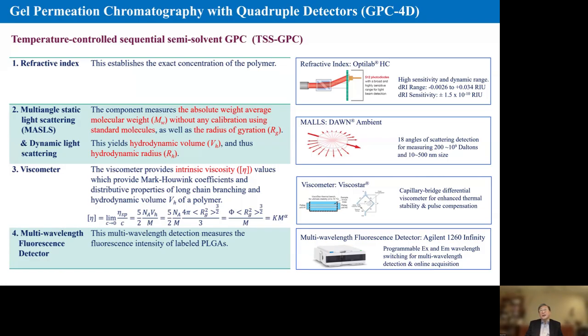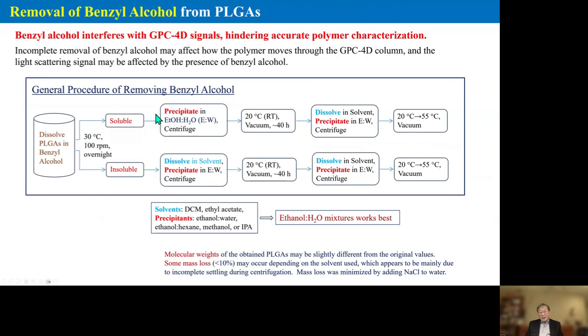Basically, we can calculate the molecular weight, absolute molecular weight, from light scattering or intrinsic viscosity, and so on. Now, during the process, we realized that benzyl alcohol somehow interferes with the measurement of LG ratio and molecular weight. We're talking about a trivial quantity, a few percent, and that small residual benzyl alcohol affects the results. So we had to find a way to remove every single molecule of benzyl alcohol.